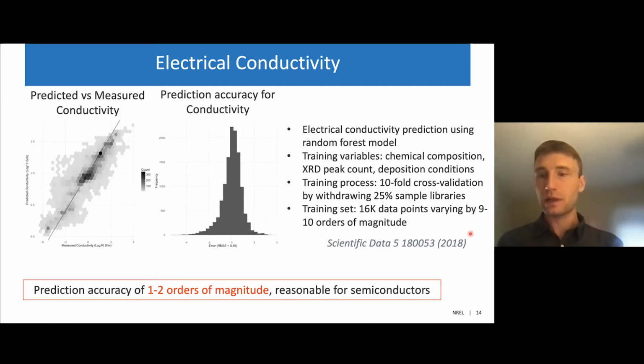So with the training set of only 16K data, which is what we had at that time when we were doing that study, we created a model that predicts electrical conductivity within the accuracy of maybe 1 or 2 orders of magnitude, which may seem like very bad accuracy, but thinking about the fact that for semiconductors, and I really mean semiconductors all the way from narrow bandgap, almost metallic materials to pretty much insulators, this quantity of electrical conductivity or doping level varies by maybe 10 or even more orders of magnitude.